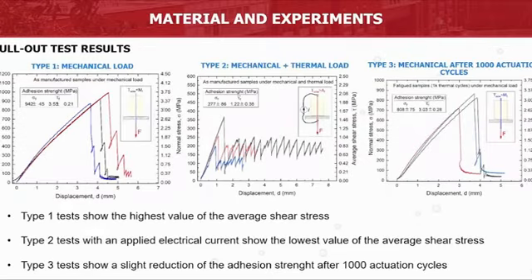In this slide are shown some results for the type 1, type 2, and type 3 of tests, and one can make some important considerations. Type 1 is the test that shows the highest value of the average shear stress. Type 2 is the test that shows the lowest value of the average shear stress.